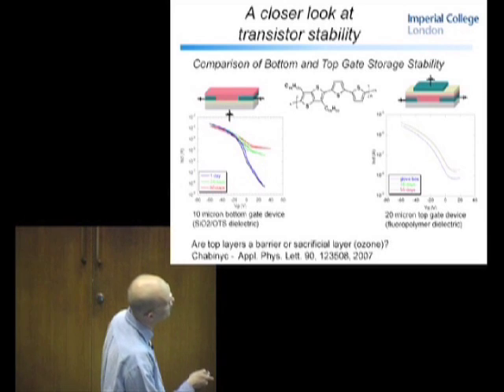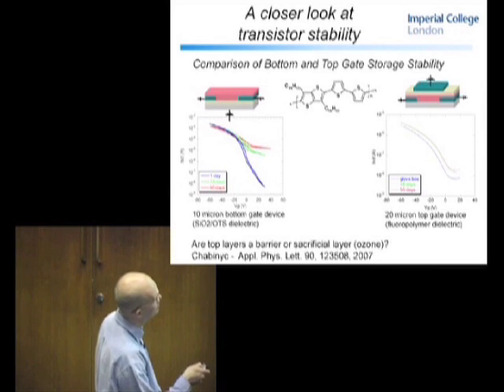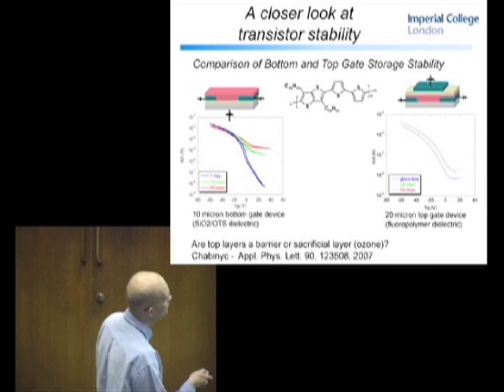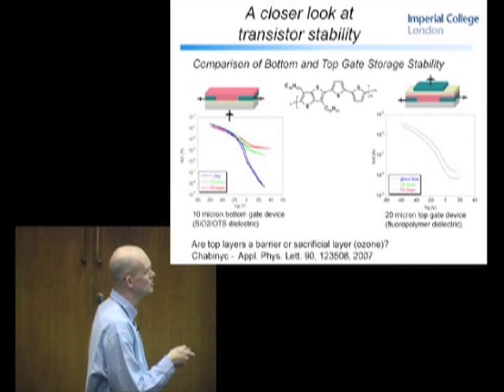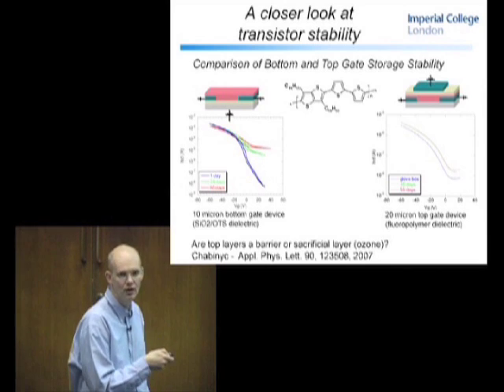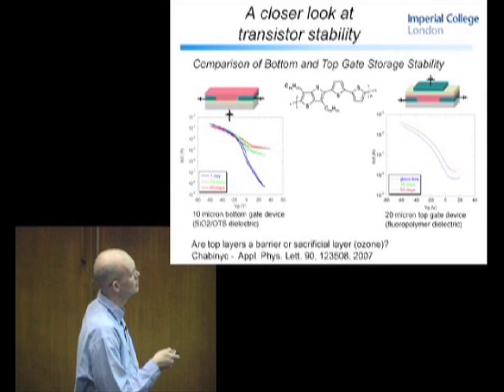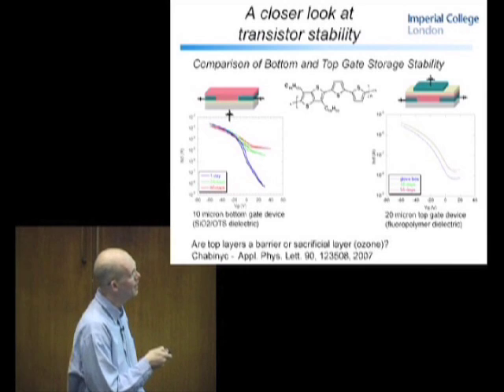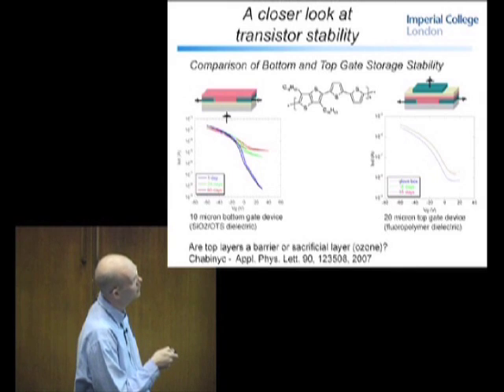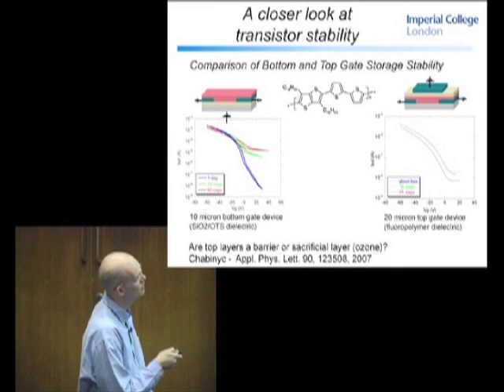But in the case of the top gate device, it's not identical, but it is pretty good. There's not a lot of difference after 55 days with this particular polymer. And so people used to think, well, it's because it's just a simple barrier to oxygen. But these are organic dielectrics, and if you think about diffusion over the course of 55 days, oxygen and ambient moisture are clearly coming through. Even PEDOT gate, Teflon or some type of PMMA type dielectrics, they're not going to be a barrier here.